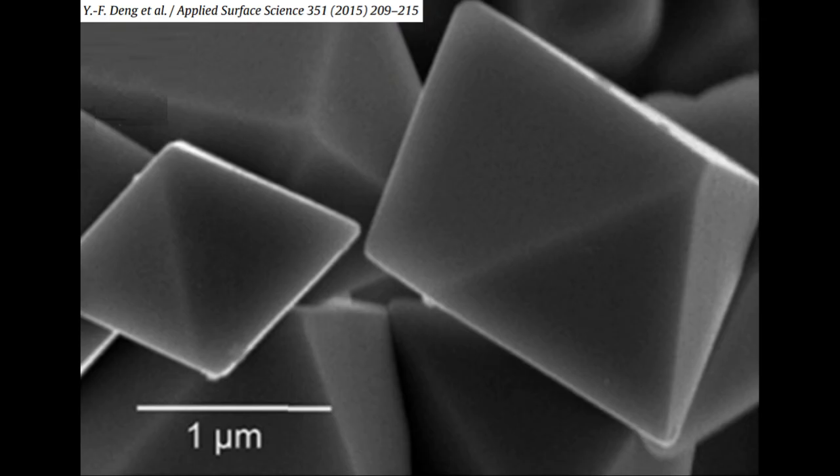locations. The second option is the single crystal cathode I've spoken of so many times before. With a single crystal cathode, large primary particles are used and there's no secondary particle structure. There are no other crystals to push against, and therefore no fracture points. It's a very first principle solution. However, single crystal cathode may cost about 2-3% more than standard cathode material, because the synthesis of single crystals requires